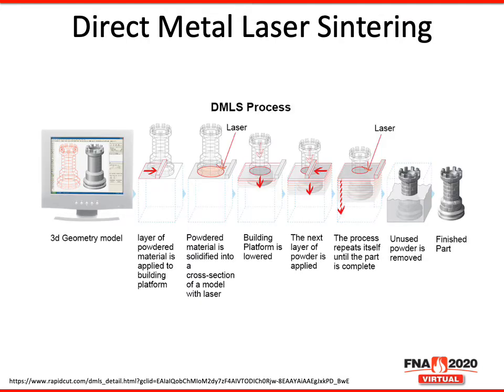So let's talk about direct metal laser sintering. First, we have a 3D model that's on the computer screen. We have a layer of powdered metal material that is applied to a building platform. The powdered material is solidified into a cross-section of a model with a laser, as you see. Then the building platform is lowered. The next layer of the powder is applied, and the process repeats itself until the part is complete. It's very important that the unused powder is removed prior to the finished part going for heat treat.